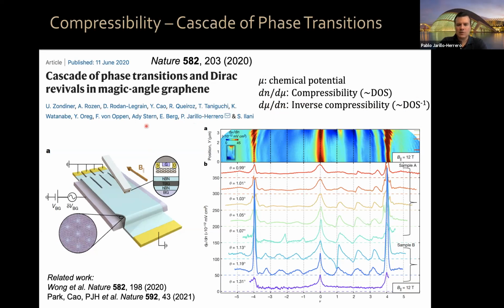In fact, what the group of Shahal Ilani does is they have this very interesting technique where they have a carbon nanotube single electron transistor at the end of an AFM tip, which they can scan on top of your sample. So we have a magic angle graphene sample, and locally they could go to different spots in the sample. Different regions have slightly different twist angles, so they could measure the inverse compressibility at all of these twist angles. So here you see this set of traces. The different colors correspond to different regions in the device where the twist angle varies slightly. You start from 0.99 degrees.